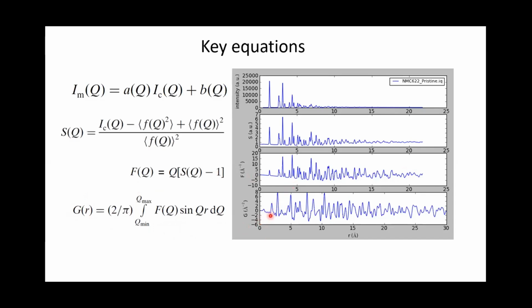So for example, this is about the 2 angstrom, indicating that we have this kind of a 2 angstrom atomic correlation, which corresponds to transition metal oxygen. And we have this 2.8 something, which is transition metal. But you do actually see some of the small peaks here, right? It looks like they do not have a clear physical origin or some clear atomic correlation.